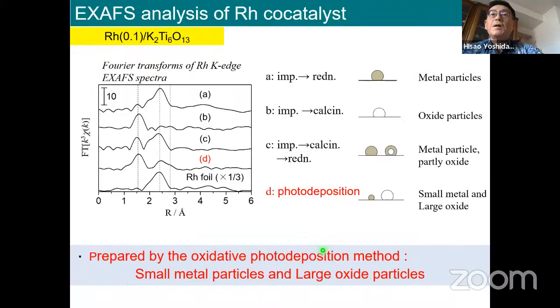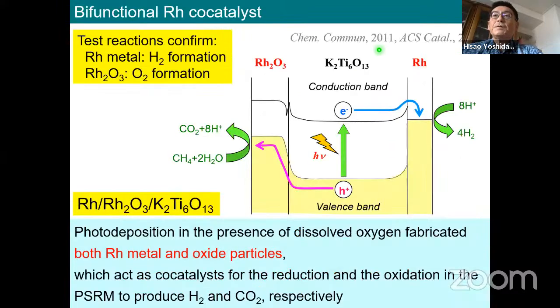So we confirmed the state of the co-catalyst by using EXAFS to know the local structure of the rhodium. In this case, the best catalyst has 2 types of rhodium, and we concluded this band energy diagram: the photocatalyst is here, and the co-catalyst is here. Rhodium metal can receive the electrons from the photocatalyst to promote the reduction reaction, and rhodium oxide on the surface, in a little bit larger particles, can receive the holes from the photocatalyst to promote the oxidative reactions, to oxidize the methane and the water, and totally the efficiency of the photocatalyst was improved.